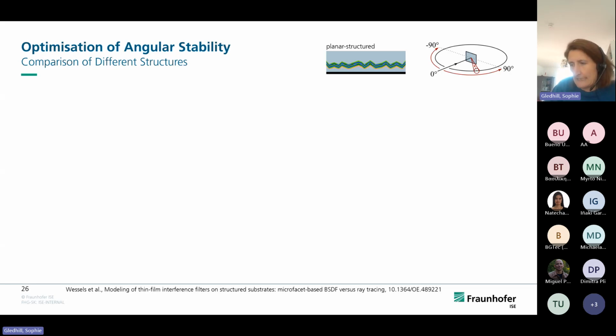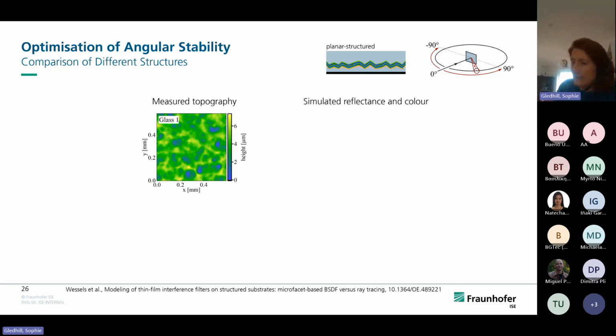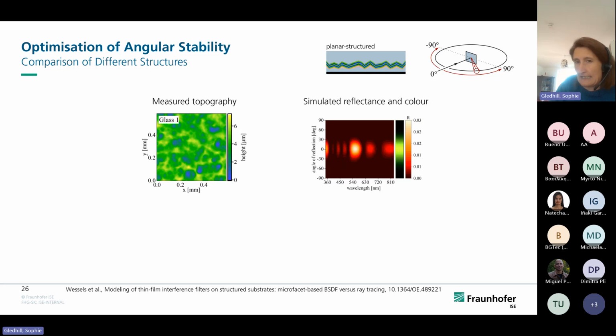So a large portion of the development work has been to improve this angular stability. This has been carried out practically by looking at different glass structures and measuring using a spectrometer and a goniometer, or photographing at angles to visualize and quantify the angular color reflection. Starting with a structured glass, a 3D measurement using a laser microscope of the surface and height data was attained, as depicted. The measured surface was used as an input for ray tracing scenery. The exact modeling is explained in the paper referenced here, and I don't want to go into details. It's not my work, but basically Andreas Wessels, our PhD student, uses his ray tracing modules and calculates the simulated reflections and color as a function of angle.